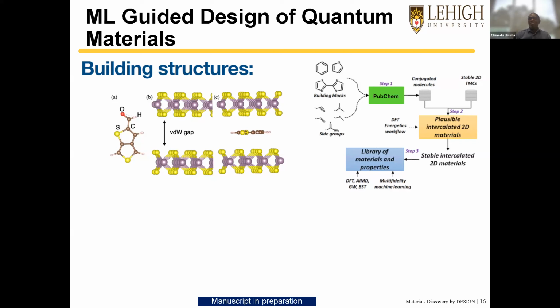for computational feasibility, because if the molecule is too large, it becomes generally an NP-hard problem because we still need to do a GW calculation and the Bethe-Salpeter equation. We need to still solve that, which is highly memory intensive, that if the size of the molecule is too large, we generally won't be able to simulate it. So with that, we form plausible intercalated 2D structures. We do some mechanical calculation using our internally developed toolkit, LS2, to tell us whether they are mechanically stable. And once we do that, we generate a library of material properties.